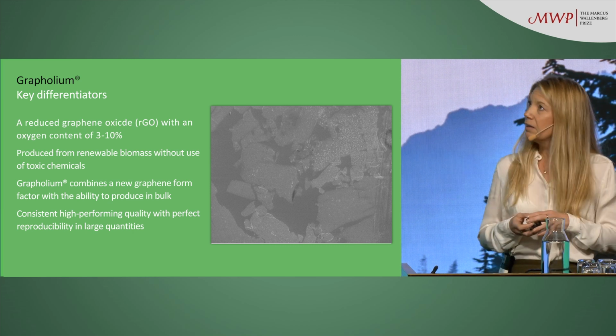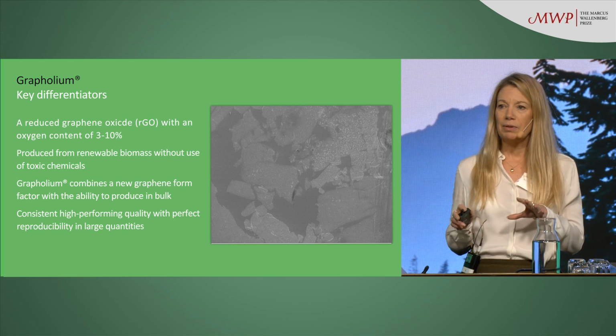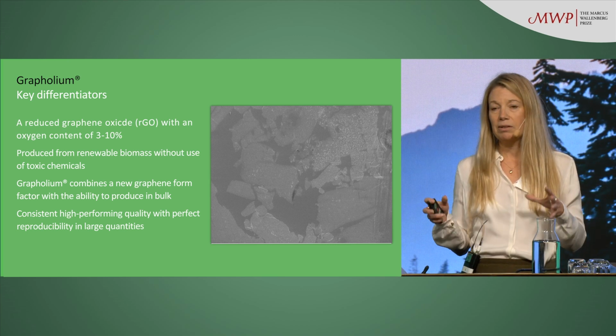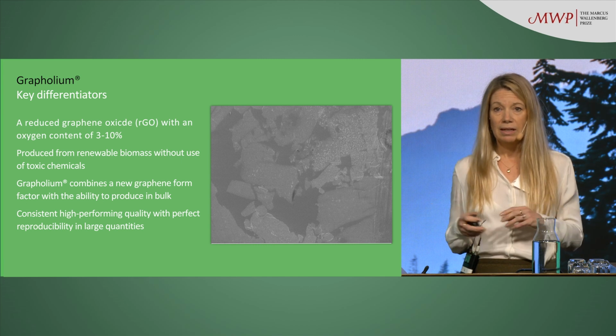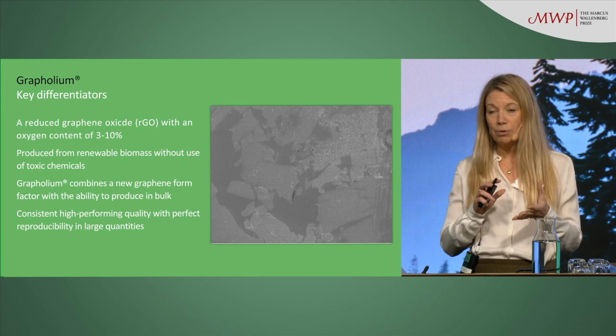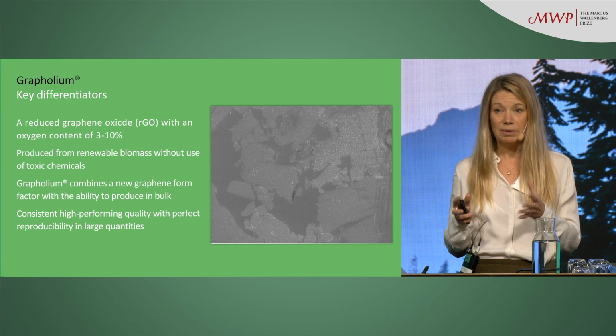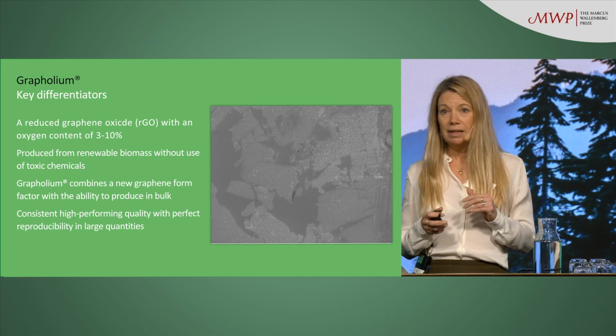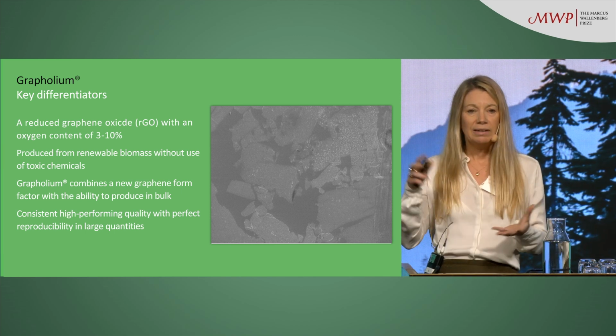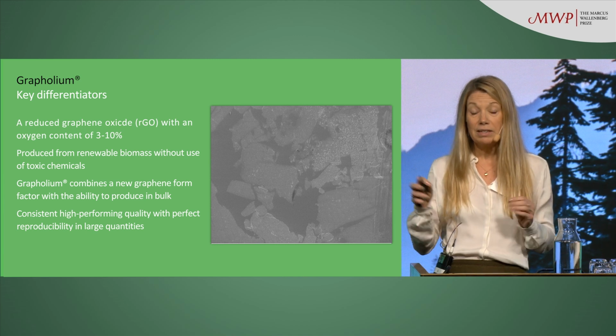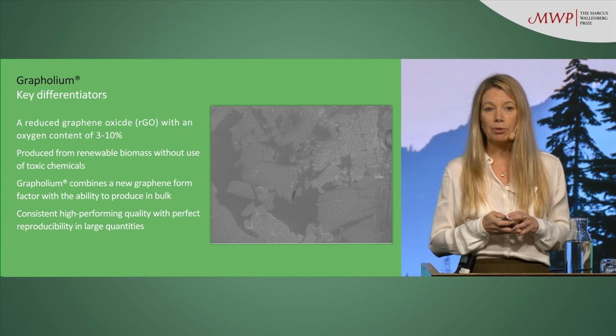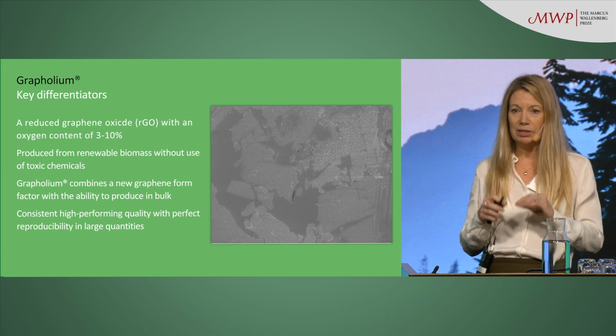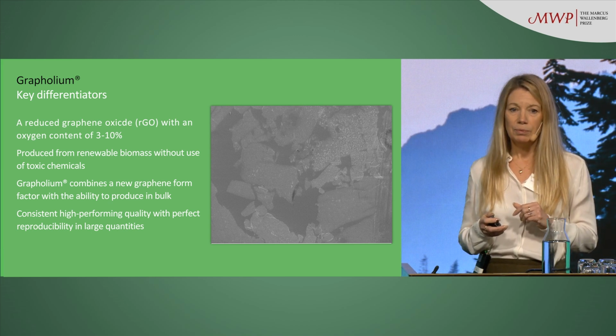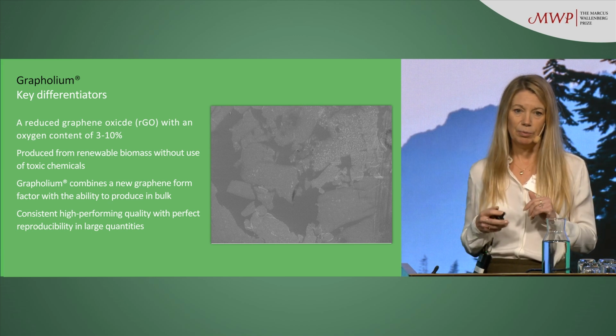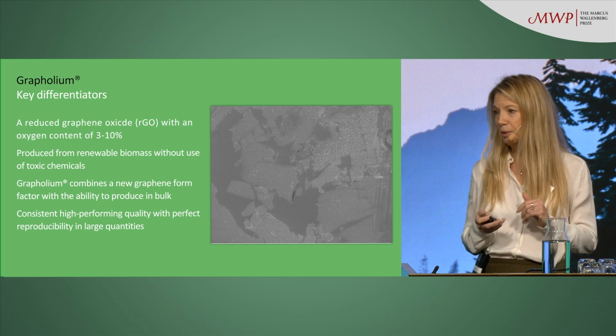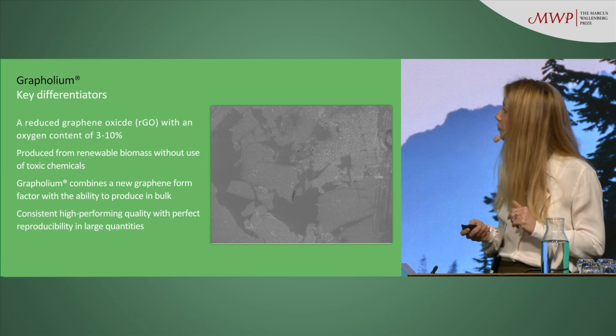And another good thing about the way we produce it from lignin is that we get a more controlled process. When you produce from graphite, the quality can differ from batch to batch, depending on the quality of the graphite. You also get a wide variety of the size of the flakes when you make it from graphite, while here we get a much smaller variety. So the reproducibility of the process is a lot better when you make it from lignin than from graphite.